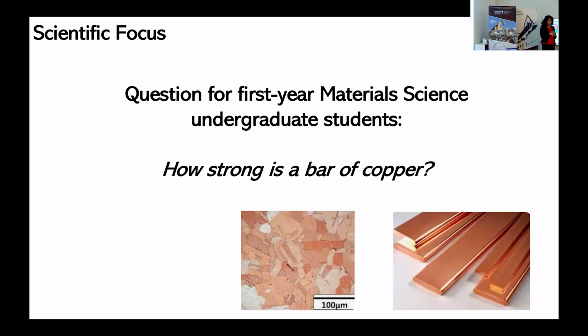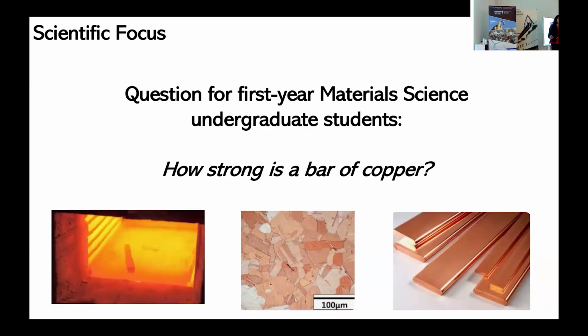If you look closely at what's inside, these copper bars are actually made up of lots of little tiny copper grains, crystallites of copper. And depending on the size, the number of grains and the number of grain boundaries, the strength of these copper bars can be very different. So in fact, the one that I had was an annealed copper bar. So the grains were slightly larger, with fewer grain boundaries. So dislocations could move more freely, which is why I could bend it. Whereas the poor person next to me was left with one which had loads of grain boundaries, which made the material much stronger. And what is the difference really? Well, it's exactly what I said. I annealed my piece of copper, right? So there was something about the processing that changed the microstructure, which then gave rise to these properties that were so different.